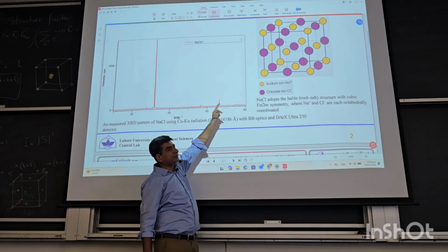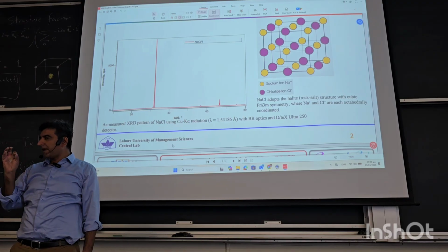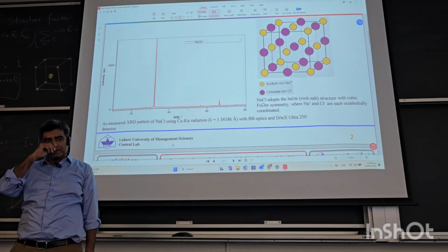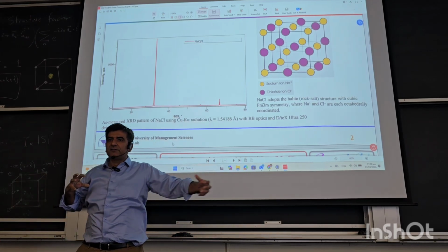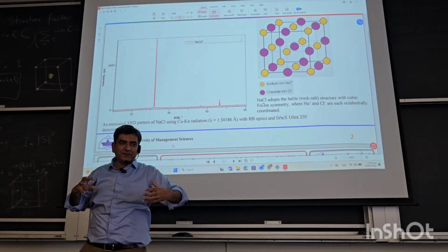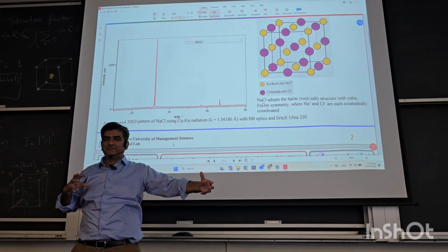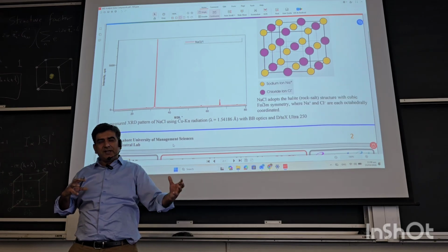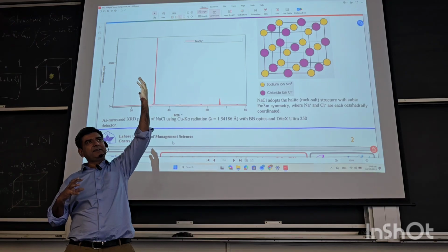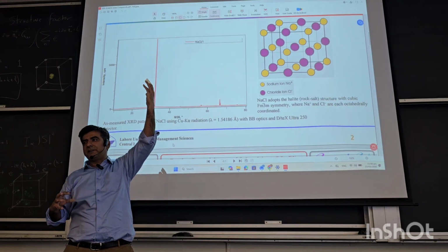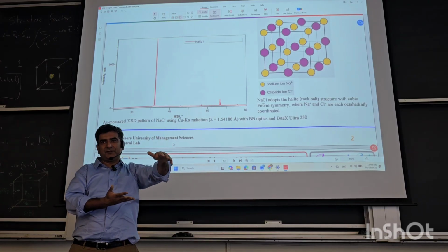These intensities are not the same because as theta goes up, the atomic scattering factor goes down. The F goes down. So you have X-rays coming in. Most of those X-rays are scattered in the forward direction because destructive interference is less likely to happen in the forward direction. For angles bigger than 0, as the angle goes up, there is a higher propensity for destructive interference from the scattered waves. So the scattering factor drops, and we can derive this as well.